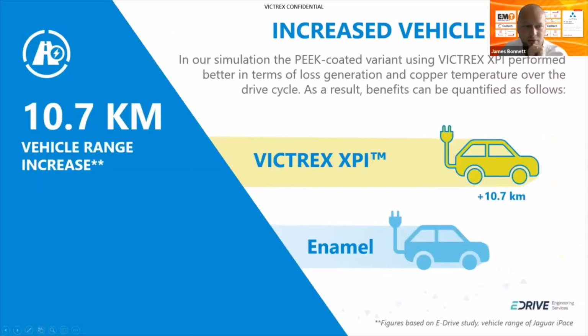What we found was when we ran our improved XPI coated wire motor through this class test, the energy consumed was reduced from the enamel model by 2%. And based on the map, the vehicle statistics, 2% is quite a significant number when we think about what that means for vehicle range.